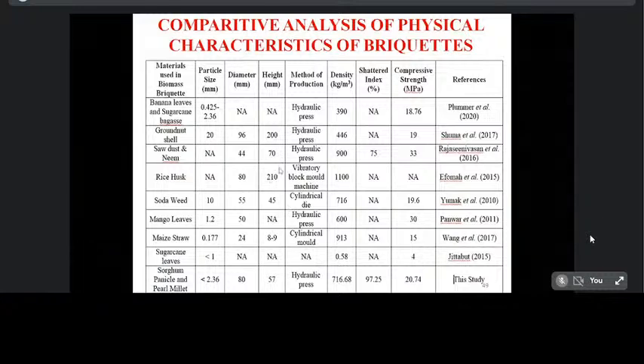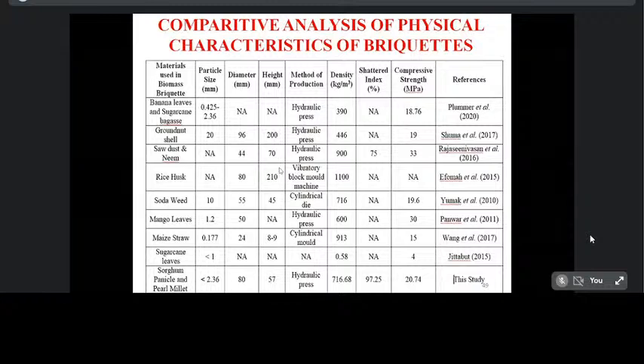So here they are producing biomass briquettes with various technologies, that is hydraulic press system, cylindrical die system, and vibratory block mold system. Okay, so the density also varied from 580 kilograms per meter cube to 1100 kilograms per meter cube. Here the produced biomass briquette has a density of 716.68 kilograms per meter cube.